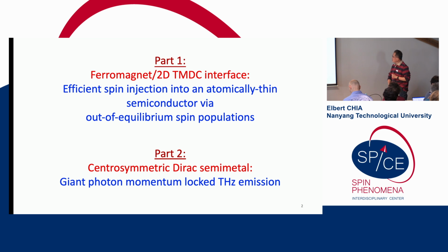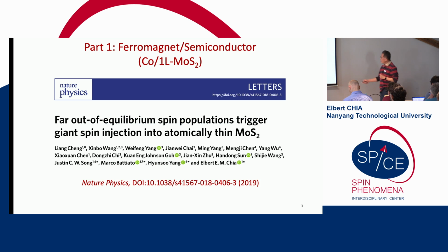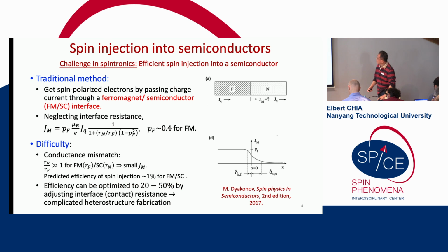So the first part of my talk is whether we can achieve spin injection into a single layer semiconductor, which is MoS2. And what we found is that we can actually obtain a giant spin injection current density. And the reason why we can do that is because we make use of the far out of equilibrium properties of the spin populations.